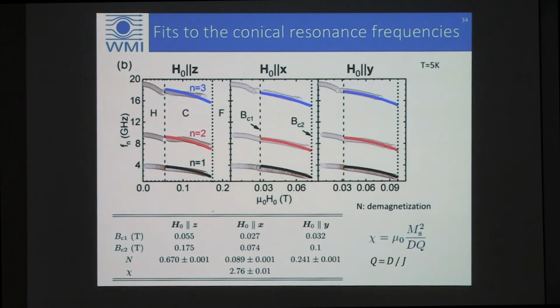So we cannot do it as a function of external magnetic field, as we usually like to do, because obviously in the system, if we change the external magnetic field, we are changing all sorts of properties of the ordering. So we have to do it at fixed field, and that leaves us, in the frequency range of our VNA, with 3 principal frequencies, and the lower one is governed by these millions of magnetostatic modes, so that drops out as well, leaving us with 2, which is perfect to do a linear fit.